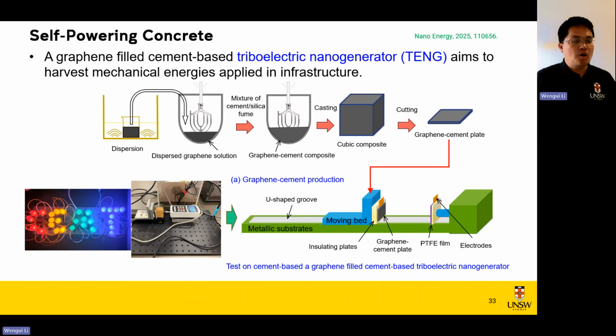For example, when we add 1% graphene by the weight of binders, we find the dielectric constant of cementitious graphene plate can reach up to 100 at 1000 hertz of frequency. So we found both the amplitude and frequency of cyclic loading influence the amplitude of the voltage and the current output. So basically, the cementitious triboelectric nanogenerator provides excellent energy harvesting capability, and which is promising for self-powering infrastructure.